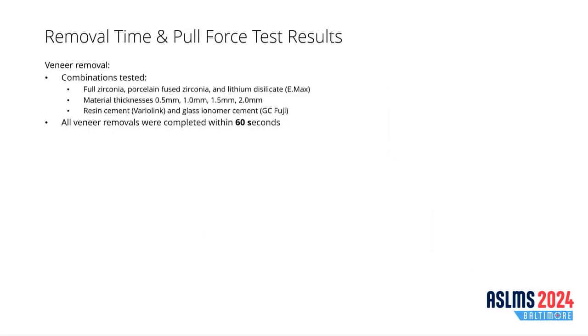For efficacy, we're looking at a decrease in the pull force necessary to remove the veneer or crown. For veneers, they popped off very quickly, within 30 seconds for the majority of them. A few 2 millimeter thick restorations remained for a little bit longer than 30 seconds.